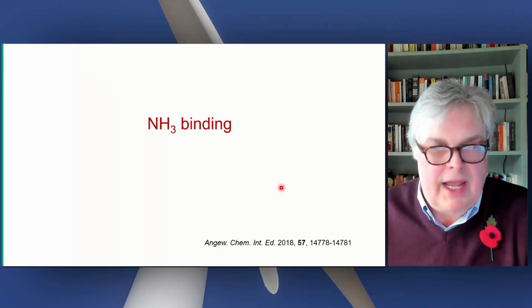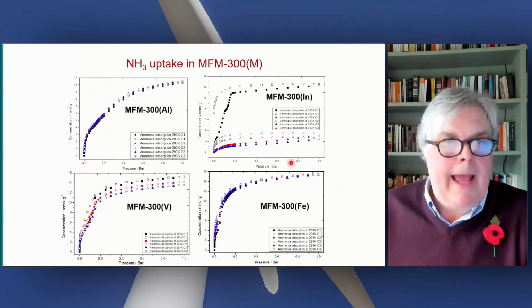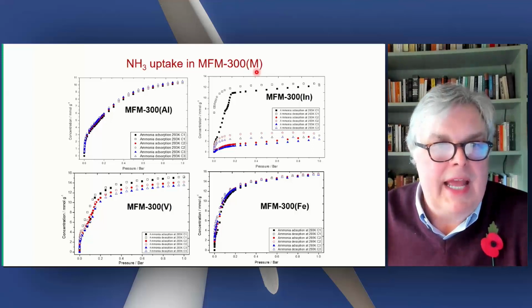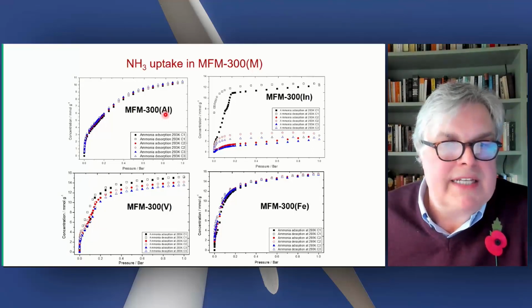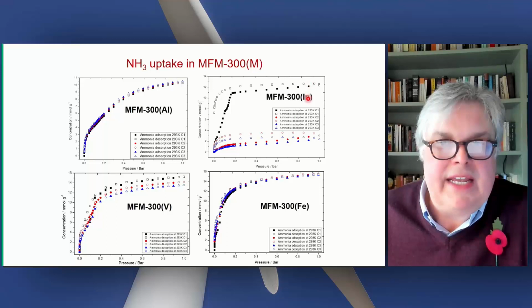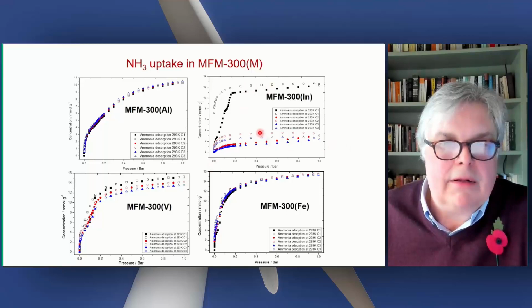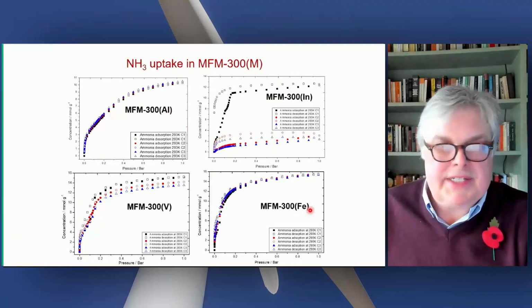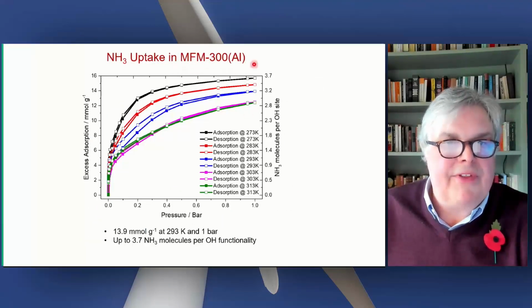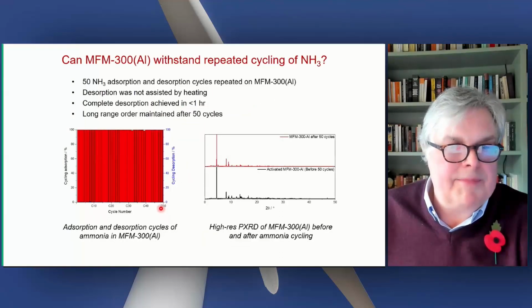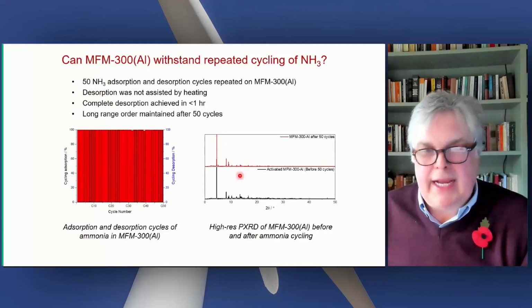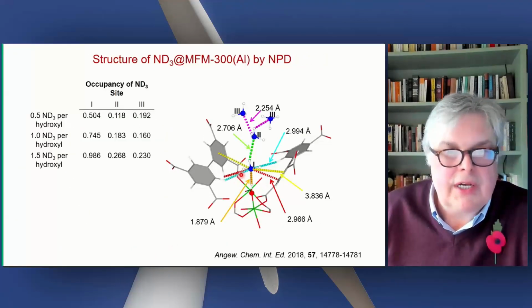Ammonia is a surrogate for dihydrogen, of course, and the MFM series is stable as long as it's aluminium or iron. You can see the indium breaks up quite quickly. This is the first uptake, and if you cycle, the ammonia uptake reduces on each cycle. Aluminium and iron are pretty stable. This is illustrated here for the aluminium compound at different temperatures. It's got very high uptake, 50 cycles with ammonia, very stable in terms of PXRD. And here is the structure.